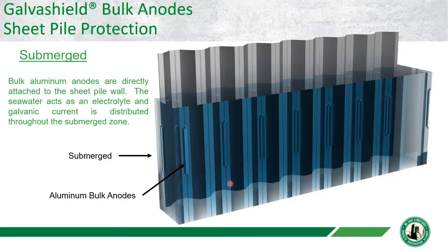So very similar to that bulk anode that we have on our concrete piles, it's going to protect everything within the submerged zone. Now it's going to depend on whether you have an uncoated sheet pile wall, whether you have just some holidays in a sheet pile coating. So the more coating breakdown you have, the more anodes.